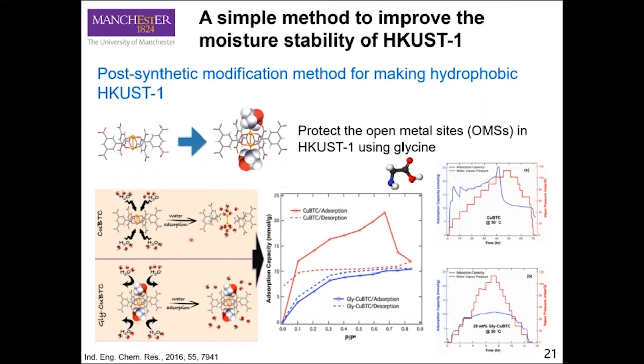The first one: if the material is hydrophilic, it prefers to bind water, and water is going to damage the framework. So what can we do? Is it possible for us to make it hydrophobic? My previous PhD student had an idea: can we use glycine? It's a very simple amino acid, and has a carboxylic acid and also an amine group. Her idea is basically to use glycine, which is dirt cheap, to dope the materials. Hopefully the carboxylic acid can interact with the copper center, and at the same time, for CO2 application, the amine group can still interact with CO2.